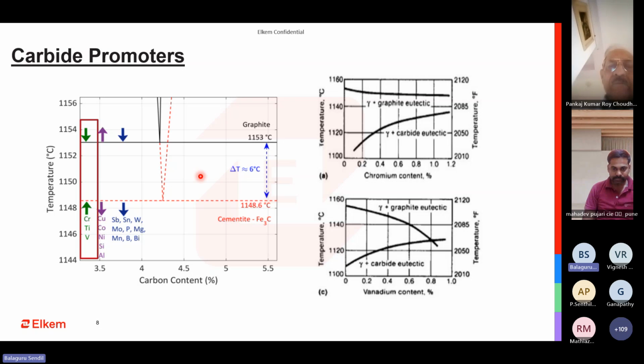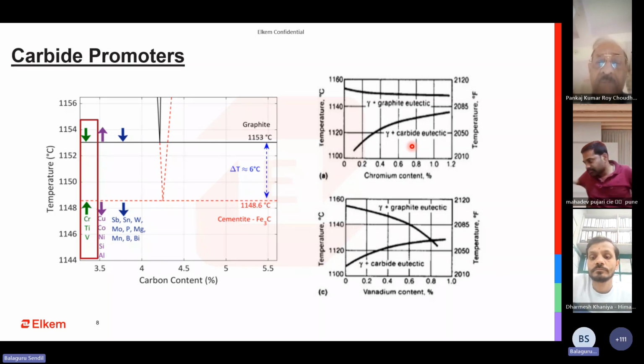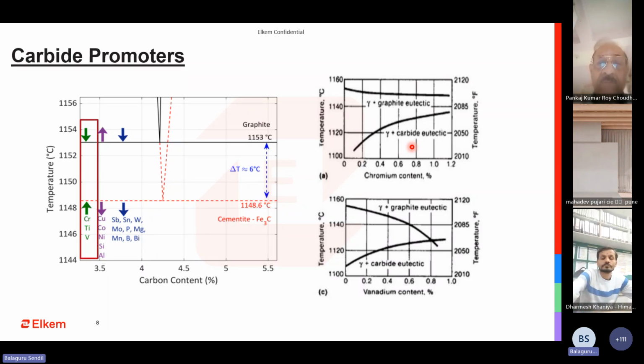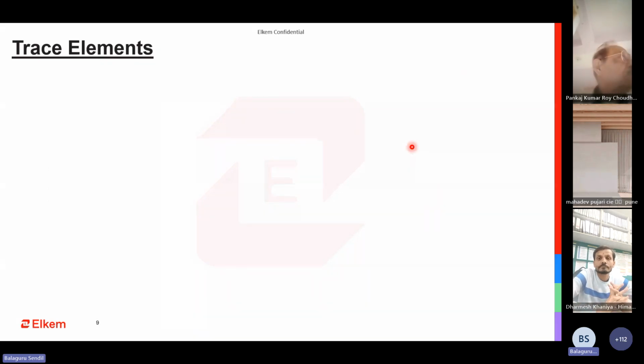If I look at it, these two charts I have just put to show how much the temperature changes that can occur when you are going with an increase in chromium and an increase in vanadium, and where it is going to intersect. So when you are having a challenge of increasing chromium, you can expect how your eutectic temperatures are going to get affected. If it gets affected, the eutectic transformation will get affected. The further transformation of iron into either austenite, ferrite, graphite, everything will get further affected down the line. And how I can correct it post tapping with respect to magnesium in case of ductile iron, or with respect to inoculation in case of gray iron, or inoculation plus magnesium in case of ductile iron again. So this is something that we should try to keep in mind, that the carbide promoting elements reduce delta T, which is much more dangerous.